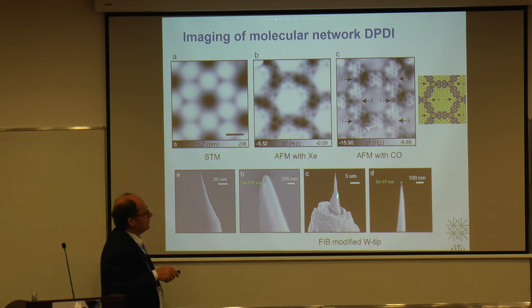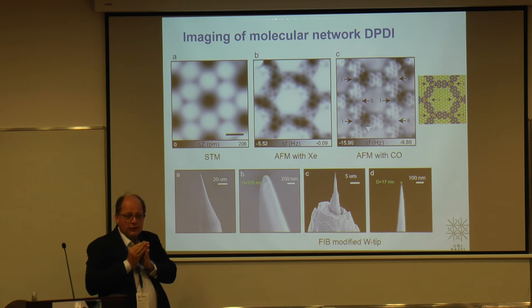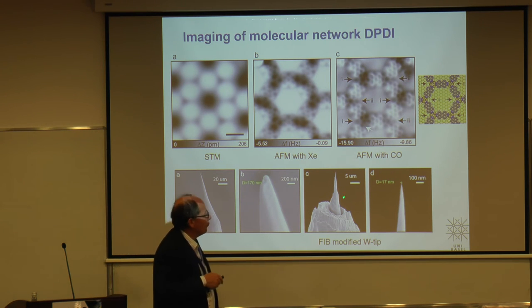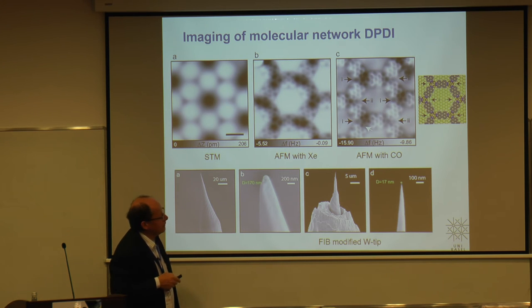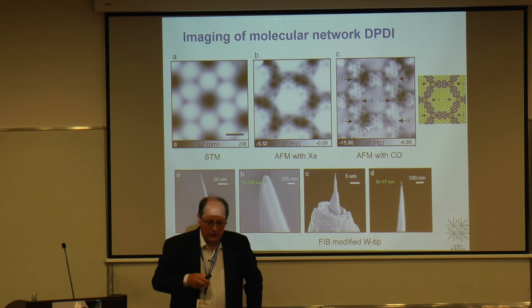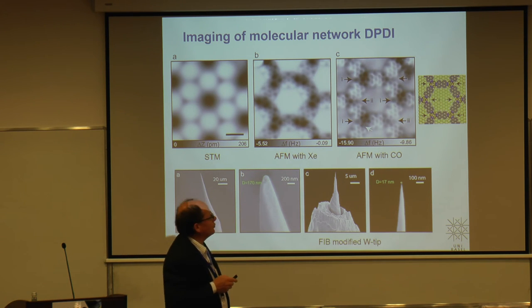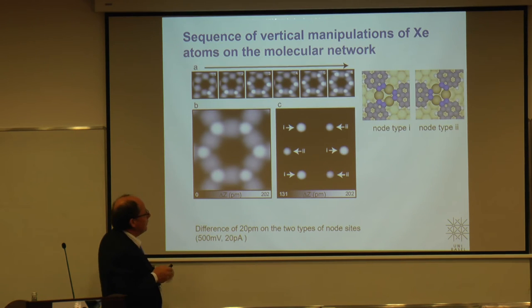It turned out for this study that it's important that you shape the tip so that it's really sharp. You use a focused ion beam, and by that you can reduce the long range forces, and by that you can finally get this atom interaction of the van der Waals forces.